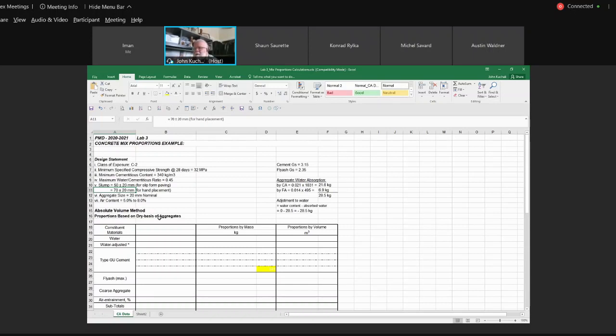Are you taking the aggregates out of a stockpile and it rained for a week, and you're now bringing it into the plant and loading it up in the bins over the scales, and that water is just dripping down? That's water that's sitting on the aggregate that becomes part of your mixing water. You've got to account for it. You just can't add water and not consider that, because now you've got way too much water. Okay, and we'll get into that.